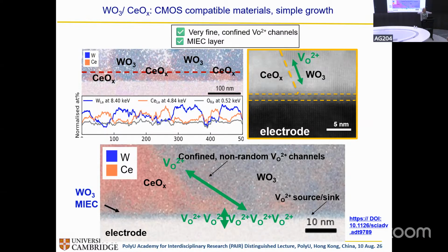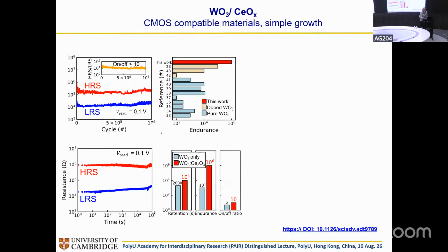The vacancies come up and down, let's say not quite straight, but up and down the film, and they can have a reservoir to go in and out of at the bottom. So that was interesting. And we had all sorts of measurements, but I'm not showing you, to prove that actually it's not a pure filamentary system, it's a confined filament. And there are many other measurements around this, but I'm just showing you how to engineer these materials, basically.